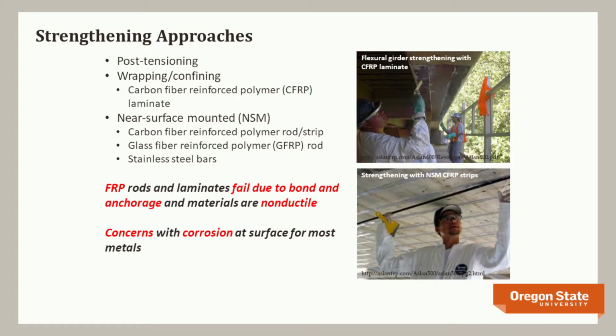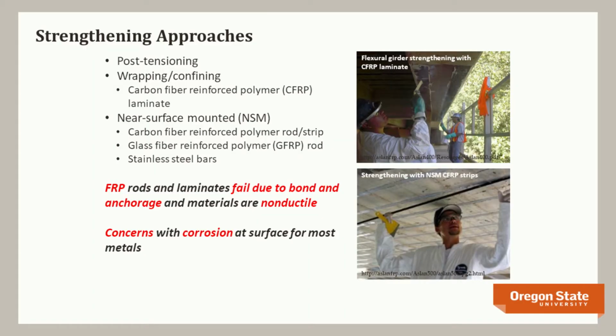And of course, there's lots of different approaches one can use, carbon fiber being the most likely material for people to look at. One of the difficulties with FRPs is that, particularly with pre-cured laminates, right, you can't bend them. And then we're relying only on, almost exclusively on bond behavior to get them. So even though they're high performance, they're non-ductile. And we don't use metallics because we're concerned about some of the corrosion issues with most metallics.